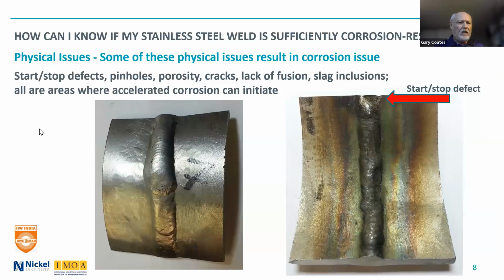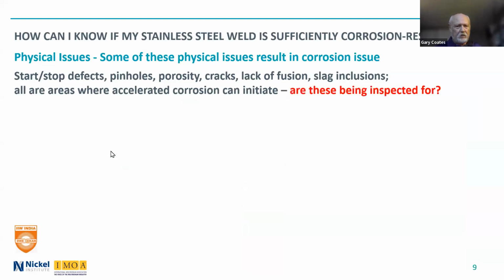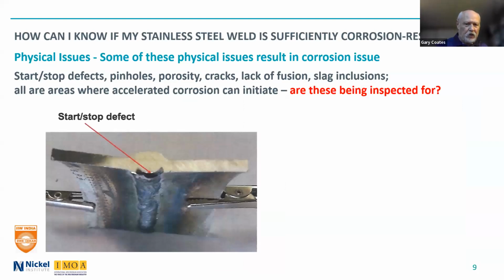This was another case where a start-stop defect caused corrosion to occur. It didn't cause a leak in the pipe at this point, but eventually it would. And again, from the outside, the weld looks okay, although you might suspect that it might not be the greatest, because it is so thick compared to the parent pipe. When you look on the inside, you see all that heat tint, and I'll talk about heat tint in a moment, and that might raise a few concerns also. But only by looking at the inside of the pipe or radiography could you actually see the start-stop defect where corrosion started. And that's just a cross-section showing the amount of corrosion that has started at the start-stop defect.